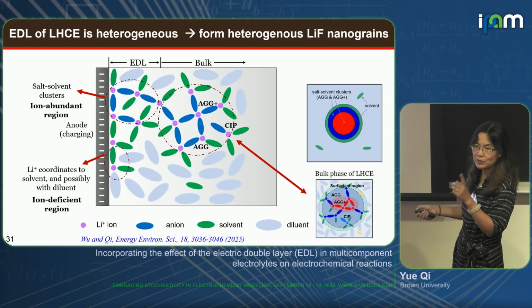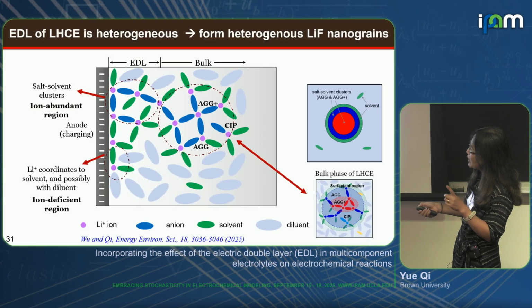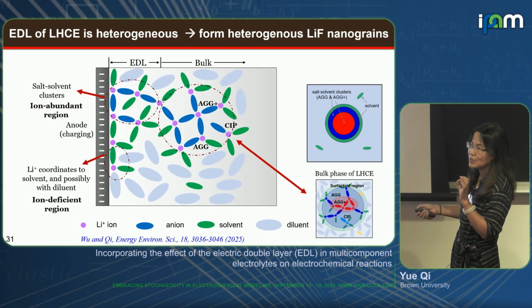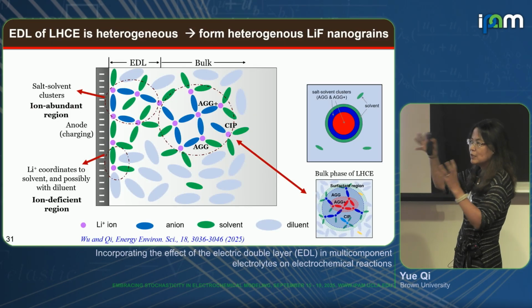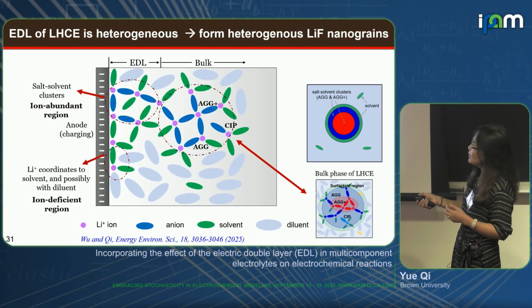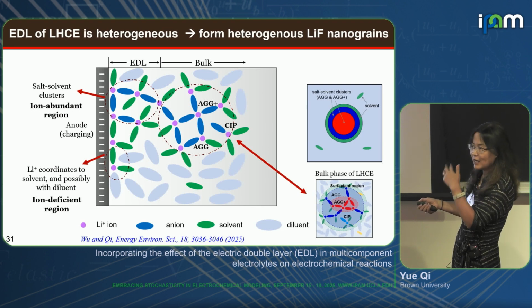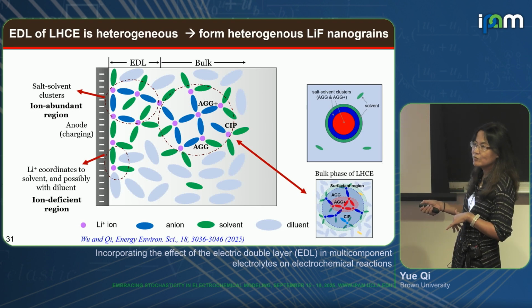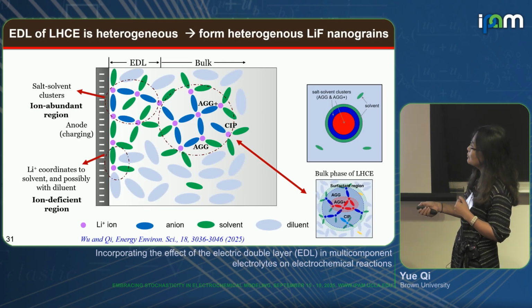This comes back to my previous question. The binding energy of this diluent and that solvent with one lithium ion is almost the same, similar. But the problem is the diluent cannot form a full solvation structure. On the surface, it's good. You saw this in the morning, that on the surface you only need to form half a solvation structure. So they can participate, right? So the diluent can participate.